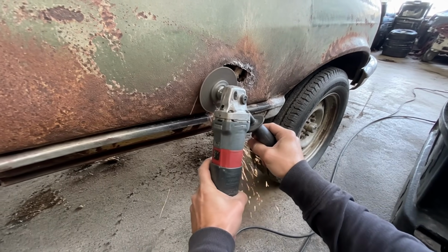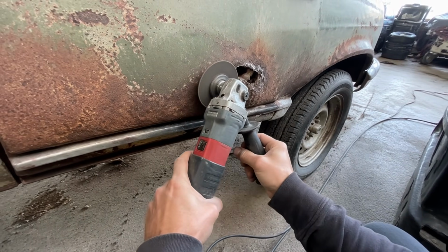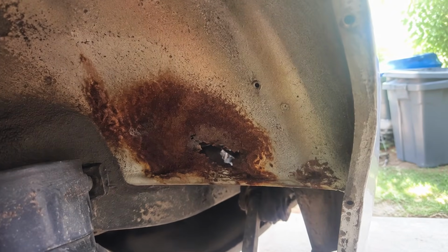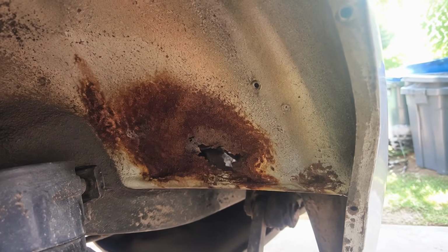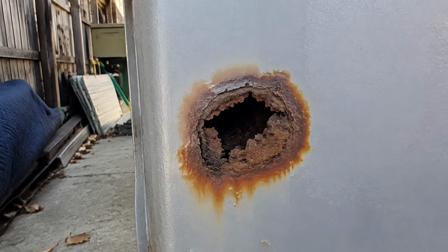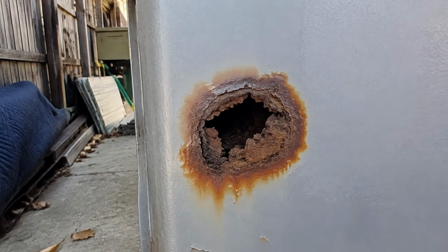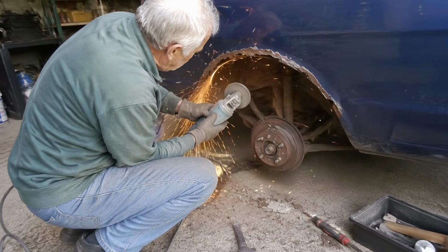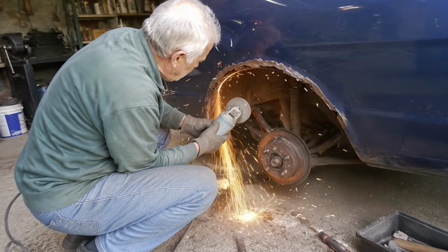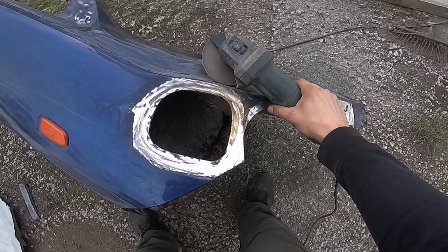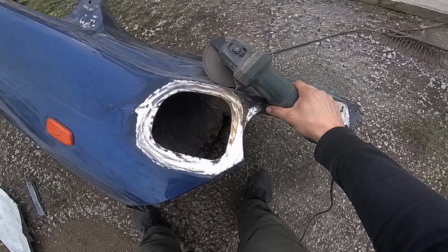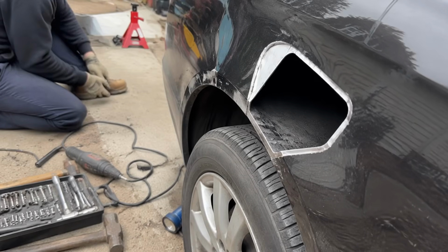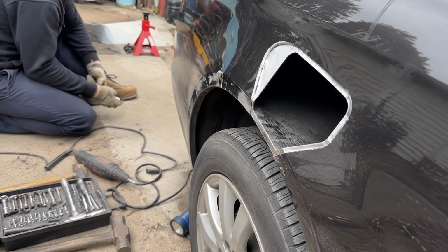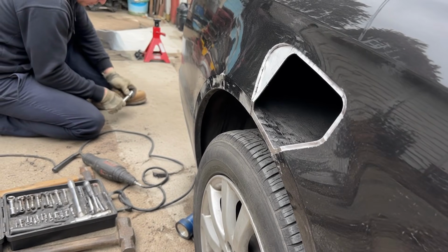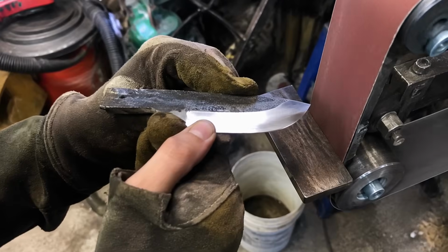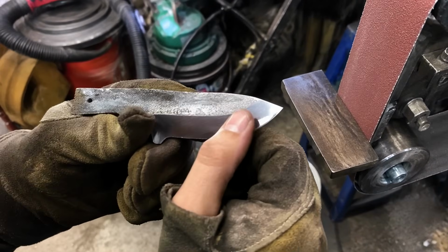First, and there's no skipping this, you cut the rot out. All of it. Remember, it's worse behind the panel than in front, so that little hole has a halo of thin, dying, half-rusted metal around it that looks okay, but isn't. You take a cut-off tool, or tin snips, or a grinder, and you cut back until you are surrounded on all sides by solid, bright, healthy metal with no pitting. This feels brutal. You're making the hole bigger on purpose. But if you leave any of that dying metal in place, the repair fails from the edges out.